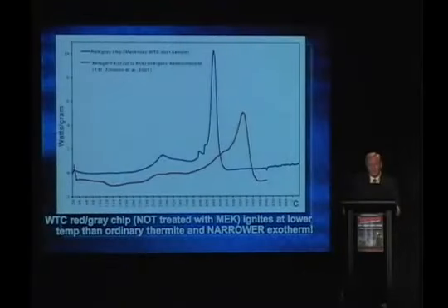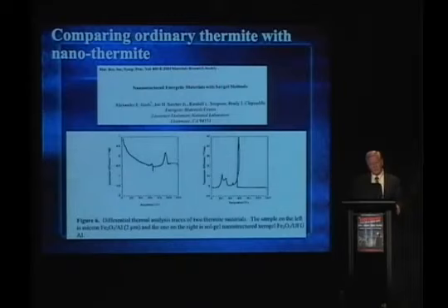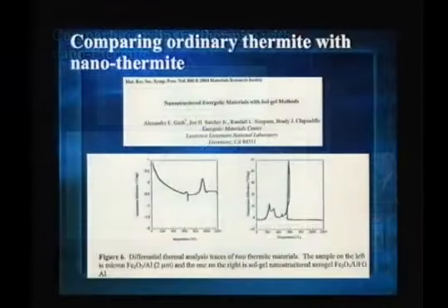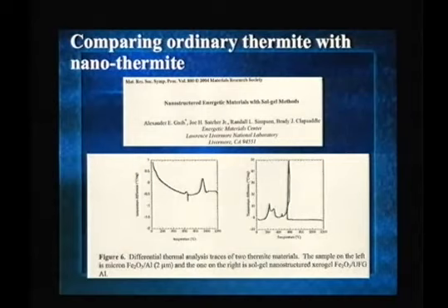The temperature at which the material ignites also tells you quite a lot about its nature. Let me just show you one thing. There's a lot of data here. You probably have to read the paper to really understand it. This is in a paper published in 2004, and again, these are the boys at Livermore Lab. On the right, we have nanothermite, a very narrow peak, around 550 centigrade it goes off. The broader peak with ordinary thermite on the left goes off somewhere around 900, 1,000 centigrade, higher temperature.